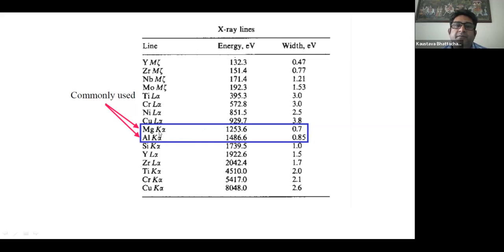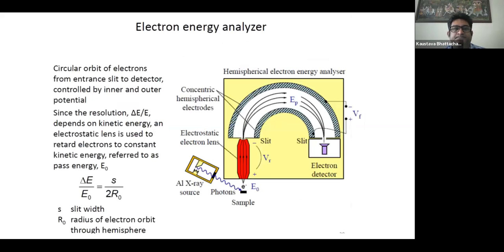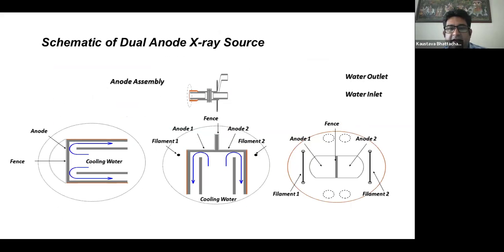If we require a much higher resolution, we'll be more often using the magnesium K alpha source. If we require higher intensity and higher energy, we use the aluminum K alpha source. Apart from these different lab sources, you can also use a synchrotron as a source, where we can tune the X-ray energy.